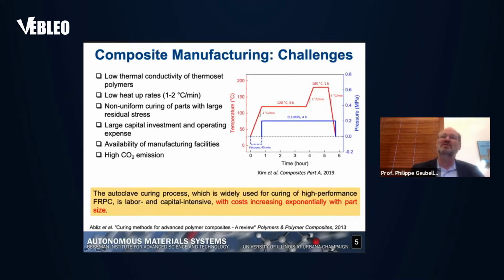These have been developed over the years due to the various limitations of the process. There is the low thermal conductivity of the thermoset polymer, so you have to use a low heat rate. You want to make sure that you have a uniform curing of the part. That complicates the control of the temperature environment inside these autoclaves. And there's a very large capital investment and operating expense for these autoclaves. There's also limited availability of these, and they generate a lot of CO2 in the process.